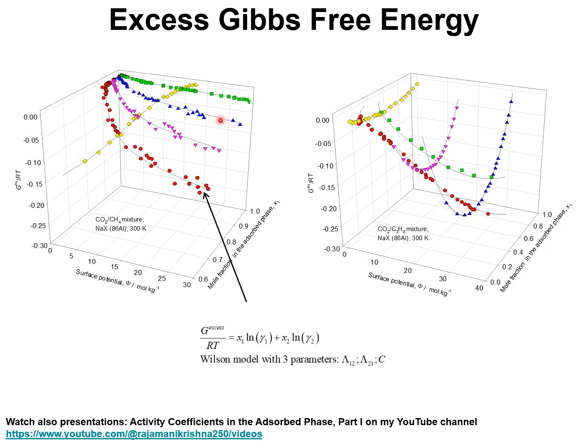In these 4 campaigns, shown by the green squares, blue triangles, inverted pink triangles, and red circles, the composition in the bulk gas phase mixtures is held constant, 50-50, 20-80, 10-90, 5-95, and the total gas phase fugacity is increased from say 1 Pascal to about 10 megapascals.